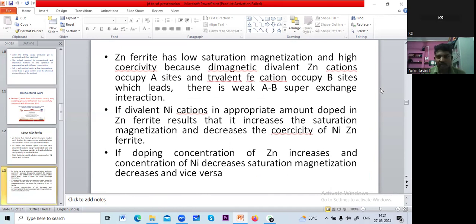Zinc ferrite has low saturation magnetization and high coercivity because the diamagnetic divalent Zn cation occupies the A site and trivalent Fe cation occupies the B site, which leads to weak AB superexchange interaction. If the divalent Ni cation is doped in an appropriate amount in Zn ferrite, it increases the saturation magnetization and decreases the coercivity of nickel zinc ferrite. If the zinc concentration increases and nickel concentration decreases, saturation magnetization decreases, and vice versa.